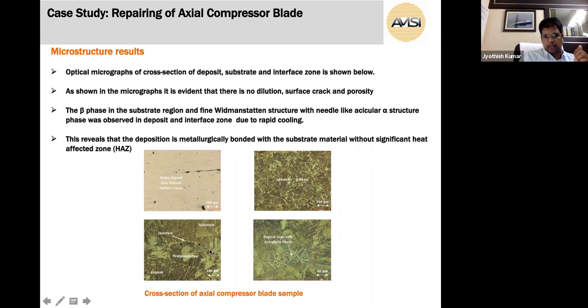This is the interface where you cannot differentiate the interface line between the deposited material and the base material, which you call the substrate. So this is evident that the LMD process is very good for repairing any existing components. And this structure shows the acicular alpha phase. That means the bonding between the layers is very good.